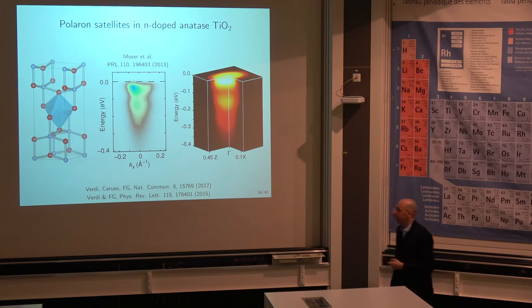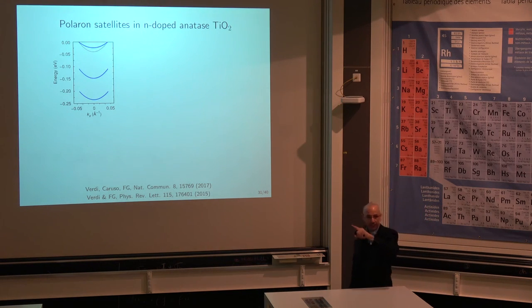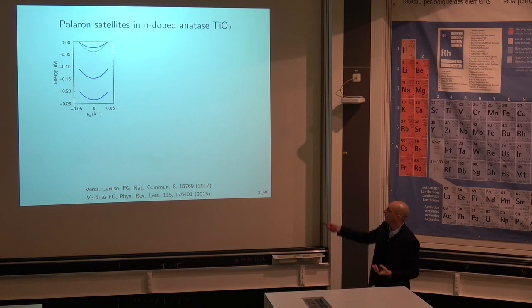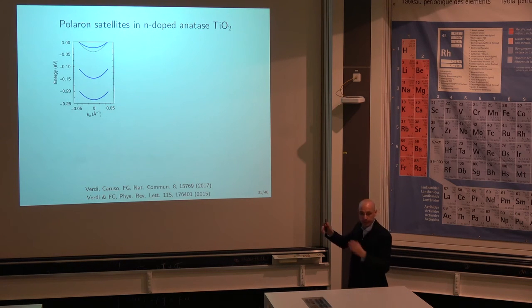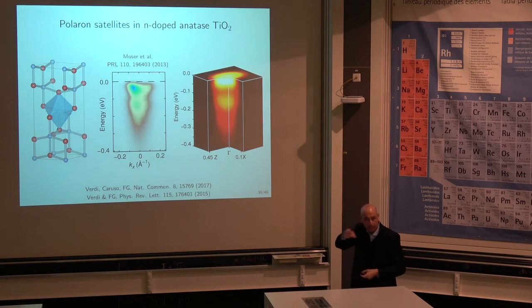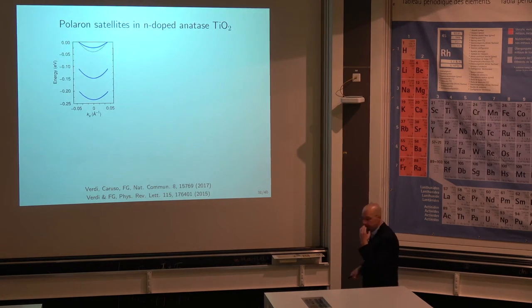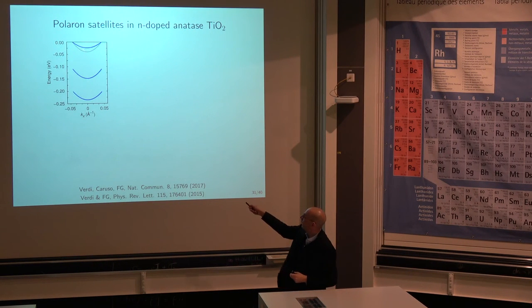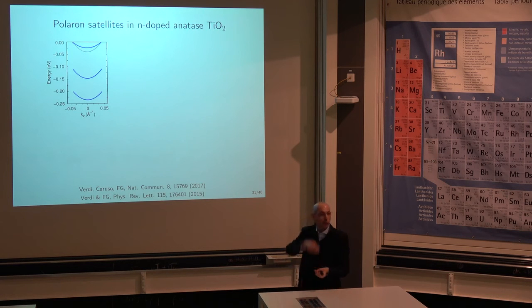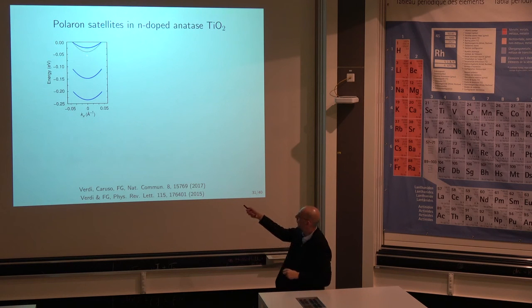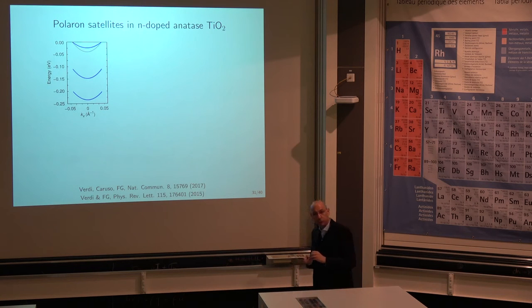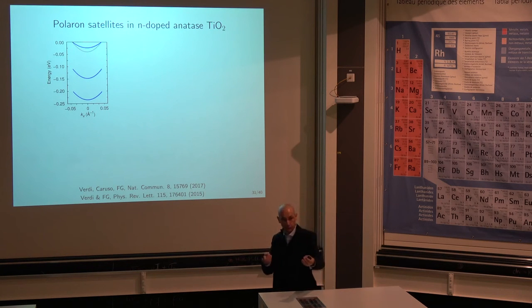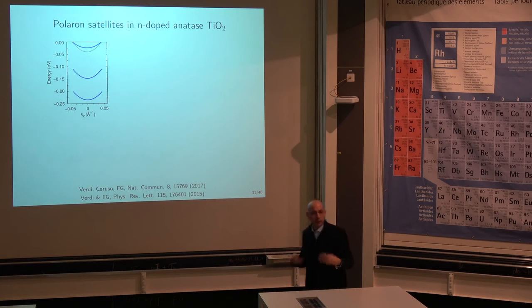Let me try to explain the physics a little bit in a simple way. If I track the maxima of this spectrum, I find something which looks like a band structure: a quasi-particle band, then a satellite, then another satellite. That's just tracking the maxima of this function numerically. So what does this picture mean? Imagine you come with a photon that has barely enough energy to extract this electron. Now imagine you come with a photon which has slightly higher energy, maybe this electron energy plus the phonon energy. What could happen is that you not only extract an electron, but you also excite a phonon. And if you have a bit more energy, you can extract an electron and excite two phonons. So how do you visualize that?